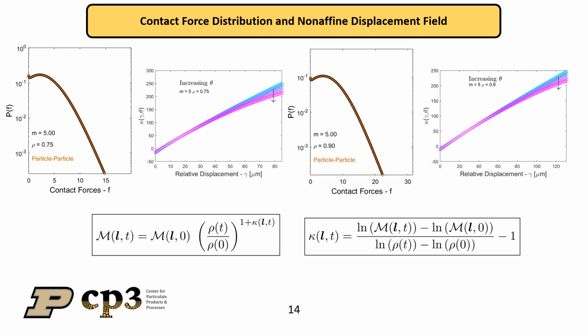We now show the predicted contact force distributions and the non-affine fields at two different relative densities for one of the example cases, particularly for hardening exponent of 5. One key thing we can see is that we can clearly see the dependence on orientation theta in the non-affine field, and we can also see that this approach captures the distribution of contact forces with high statistical significance.